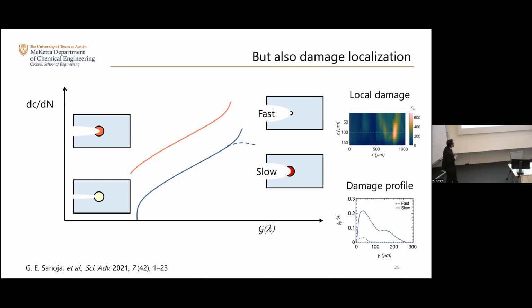So I think the physics is similar in the sense that when you start damaging the system ahead of the crack tip, you start homogenizing that stress concentration. So in my viewpoint, really what ends up giving you fatigue resistance is that you have initially a stress concentration. When you damage the system, you locally soften. And if you manage to stabilize the stress ahead of the crack tip and make it similar to the stress in the bulk, then you don't have a driving force for fracture anymore because of your Griffith criterion. After all, the Griffith criterion is telling you that you need a stress concentration to propagate the crack. If I locally damage the system and I soften locally and I create a stable state where everything is homogeneous, then I don't have a driving force anymore.